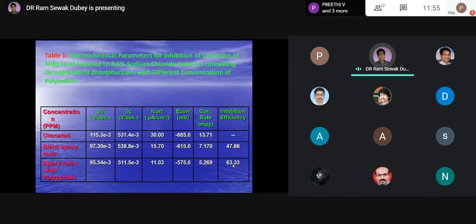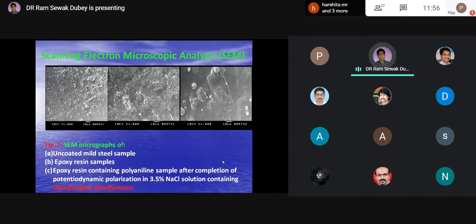This inhibition of microbial population was further verified with the help of scanning electron microscopy, where you can observe the first diagram is the uncoated mild steel sample. The second one, SEM micrograph, is for the epoxy resin only sample. And the last one is the epoxy resin containing polyaniline sample after completion of potentiodynamic polarization.